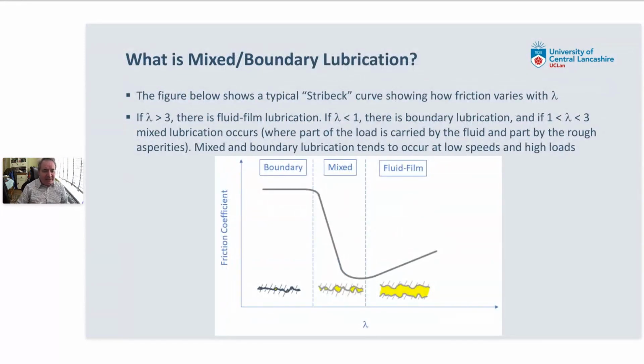So what this means is if we measure the friction coefficient, it will depend to a great extent on how thick the film is between the moving surfaces. And so the figure below in this slide shows what happens as we change the lambda ratio when two surfaces are sliding against each other. So when lambda is less than 1, effectively none of the load is carried by the fluid. All of the load is carried by the rough surfaces, and you end up with a friction coefficient which tends to be a fixed value of about between 0.1 and 0.2 typically.